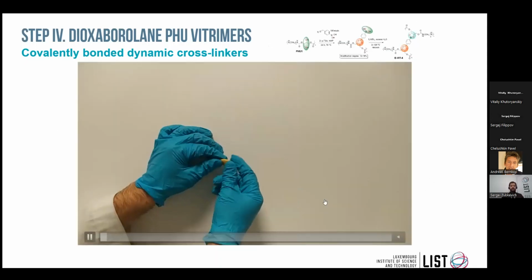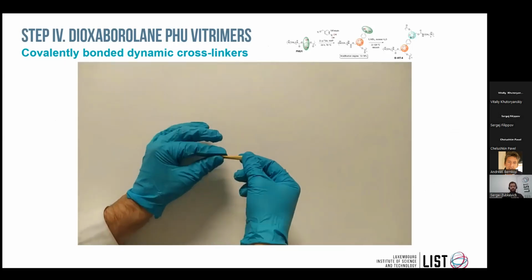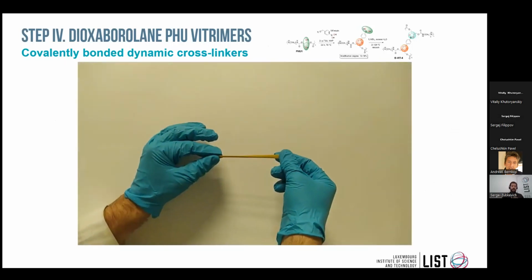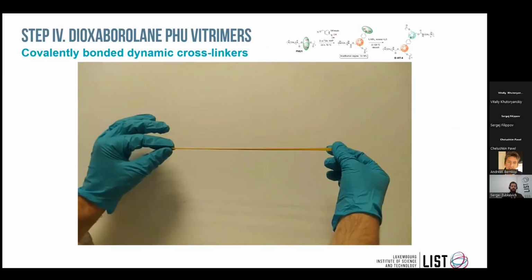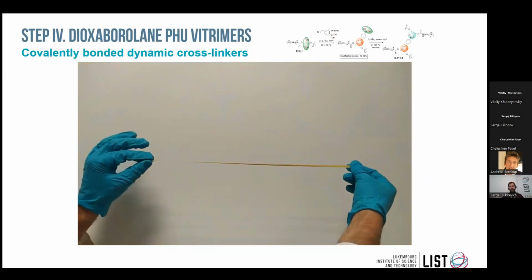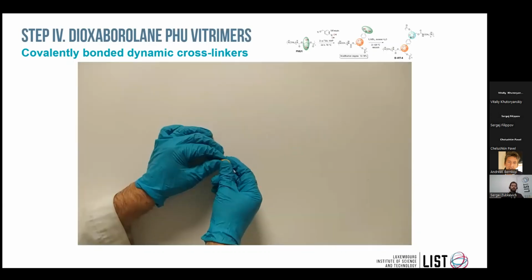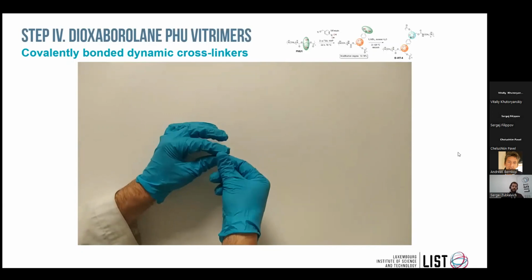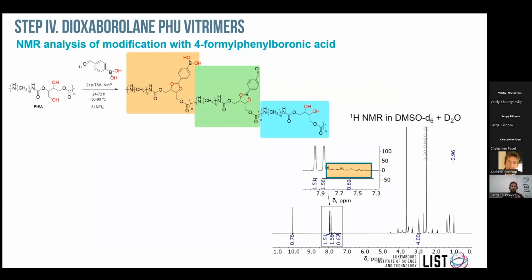And you can see that the material in its plasticized state, with a little bit of leftover solvent and moisture inside, behaves differently under stress conditions. It depends on how you stress it. If it's fast, it readily breaks. But if you slowly pull it, it relaxes with the force applied. And then you can stretch it a lot. So it's extremely stretchable, and there are papers in the literature that show it really well.